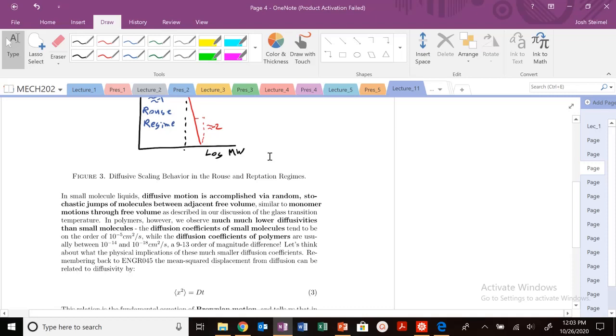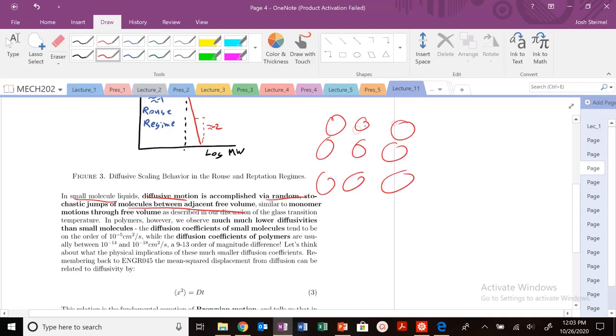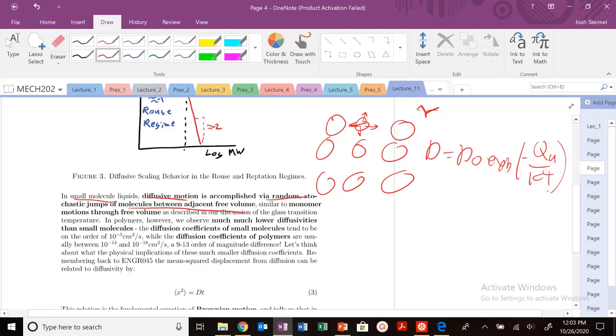Let's think about and remind ourselves about diffusivity. In small molecules and liquids, we can model diffusion as random jumps between molecules of adjacent free volume. An atom — or in metals too — we're kind of hopping, with some frequency of hopping between nearest neighbors. We know that diffusion is going to be this Arrhenius exponential relationship: D ~ exp(-Q_A / kT). As thermal energy increases, hopping rate increases, and the probability to hop depends on available free volume.